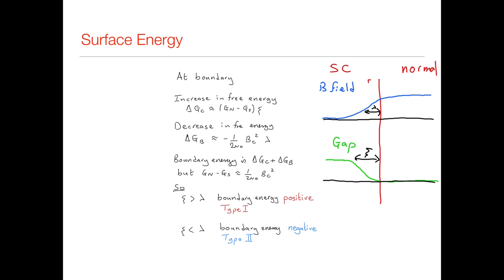Now, interestingly, we found very early on when we did the thermodynamics that the factors at the front are roughly equal to each other. So whether the surface energy is positive or negative just depends on the ratio of these two parameters. So if xi is greater than lambda, the boundary energy is positive. So having an interface costs energy, and so the material wants to have as few interfaces as possible. So it only has an interface at the surface. It has to have one at the surface, so that's the only interface that it has.